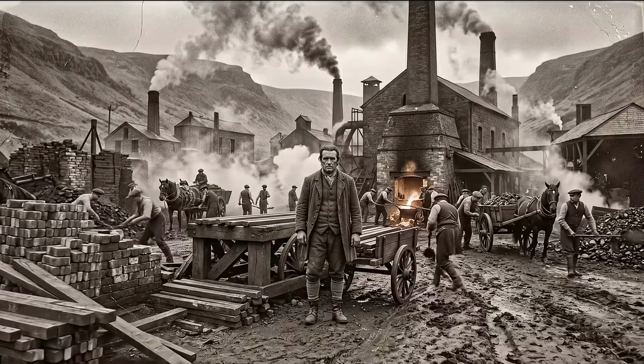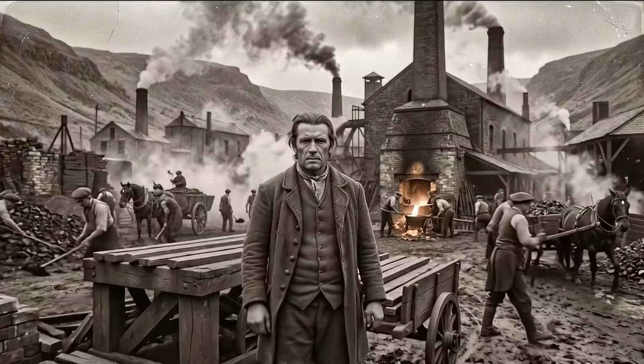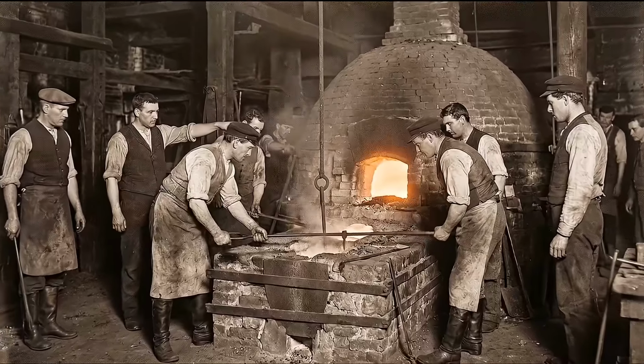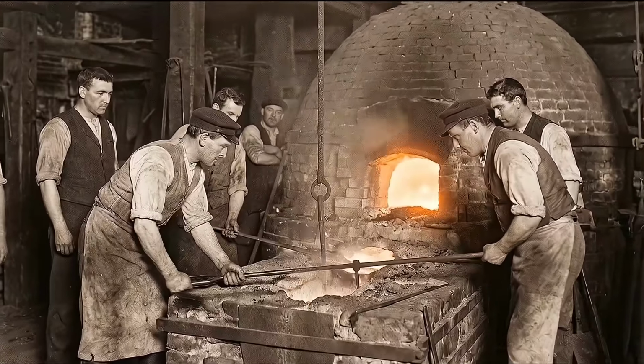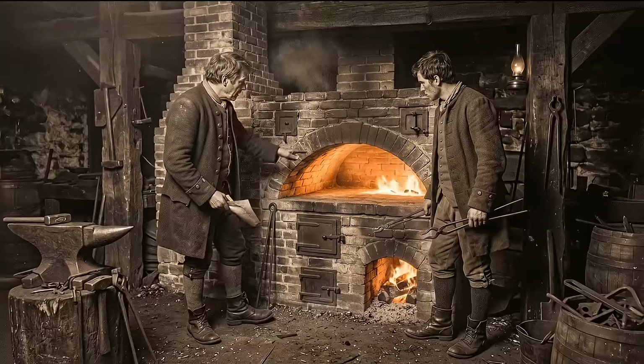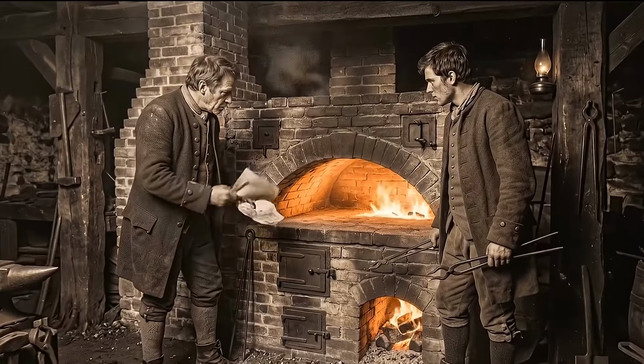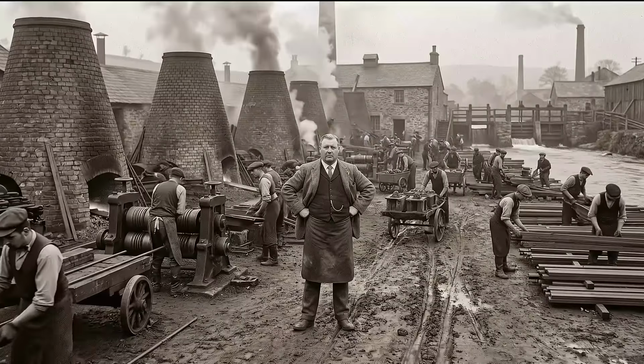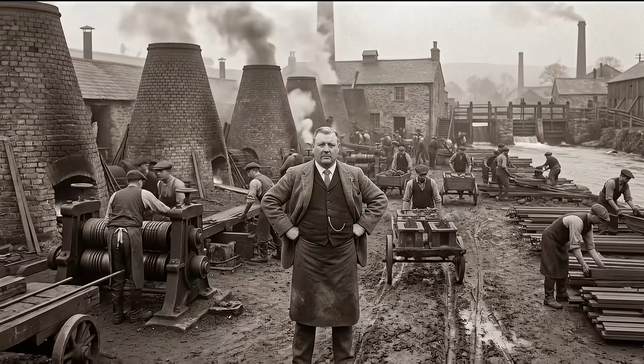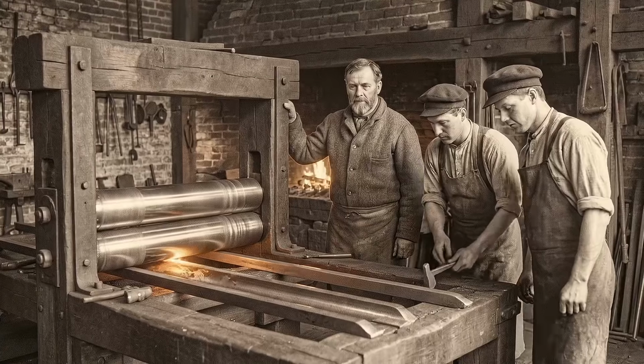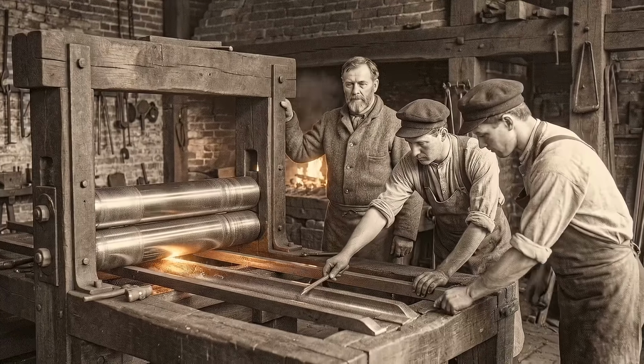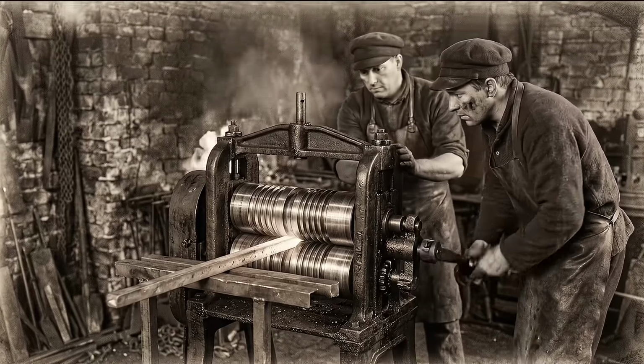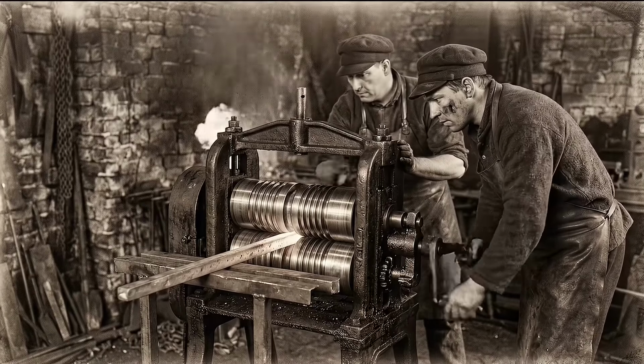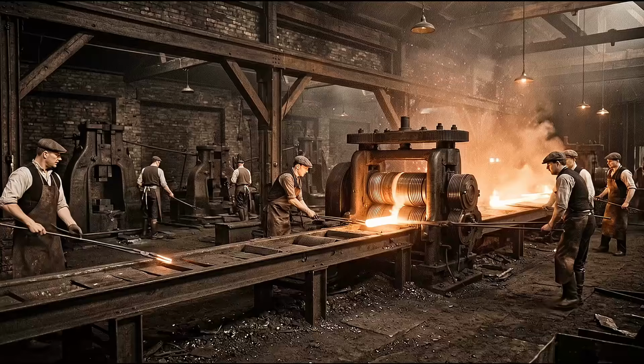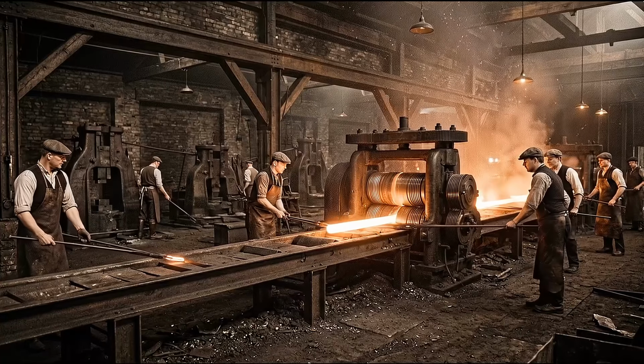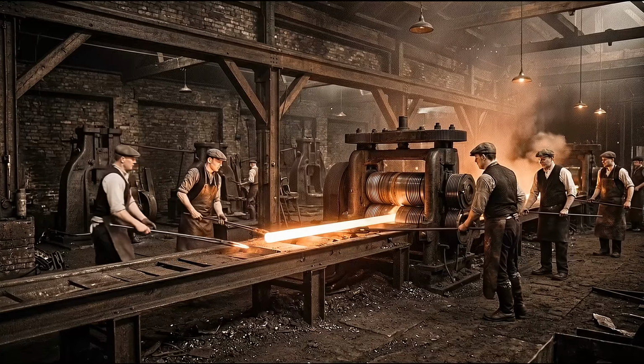A man named Peter Onions, working in Merthyr Tydfil in South Wales, had actually patented a process for stirring molten iron to refine it back in 1783. The Cranage brothers had experimented with reverberatory furnaces before that, but none of them had turned it into a complete, scalable system. Cort did. In 1783, he patented grooved rollers, a set of metal cylinders with channels cut into them that could press heated iron into bars and standardized shapes. Rolling replaced hammering, and it was roughly 15 times faster than shaping iron under a trip hammer.